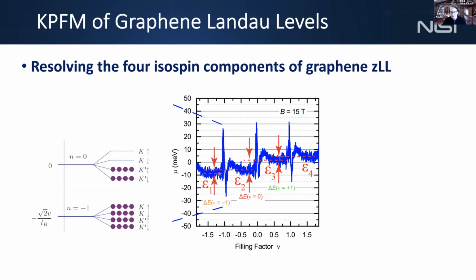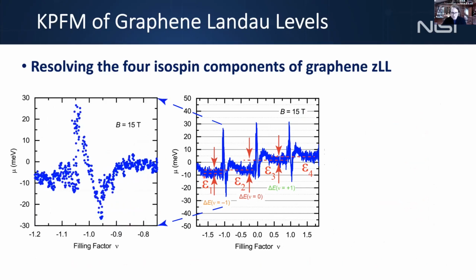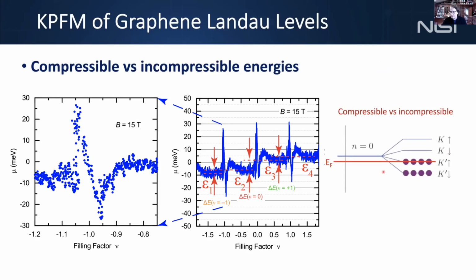And there are 2 aspects to this data. We have the plateaus here, E1 through 4. And then we also have these excursions here, these big swings in chemical potential. And these two signals come from the Fermi level moving through the different levels. The plateaus come about when the Fermi level is partially in the Landau level. So these are partially filled Landau levels. So when we go from Landau level to Landau level, like this, we get a measure of these different plateau energies.